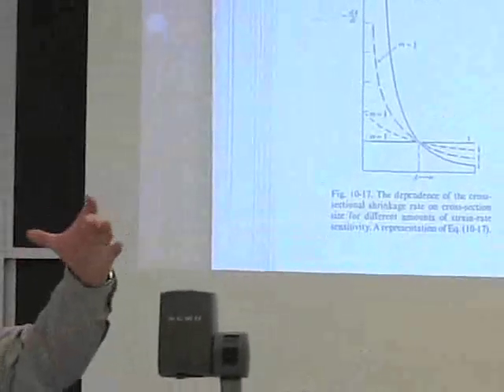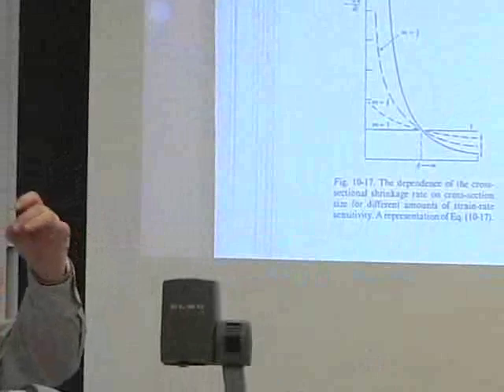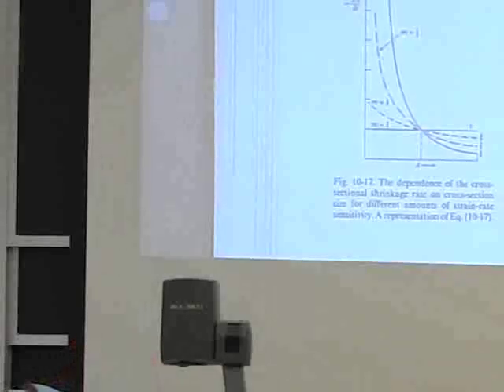But then they had to draw that down. Well, it turns out glass, fortunately, is the closest thing we know in the world to a Newtonian fluid when you heat it up. It has an m value of 1. So when they heat it up, they basically have something that heats this glass rod, and they just pull a fiber out of it. Okay? And they pull it for thousands of miles. You know, they just keep coiling it, and just keep pulling it using temperature as a dieless drawing operation.